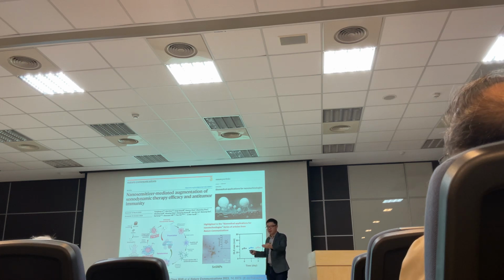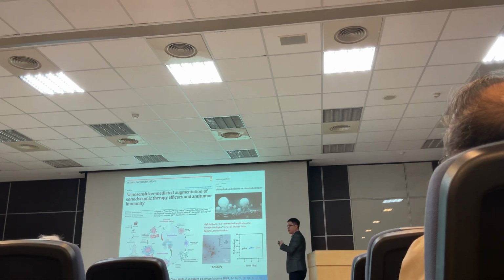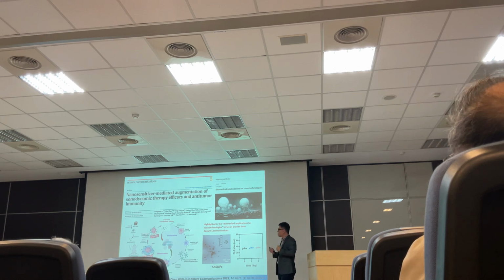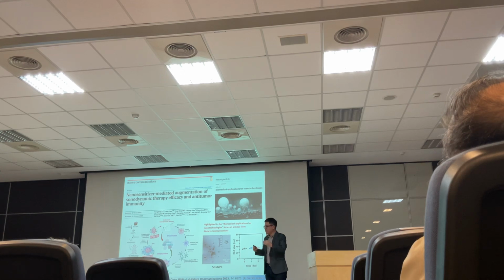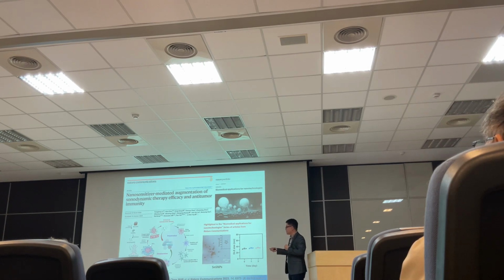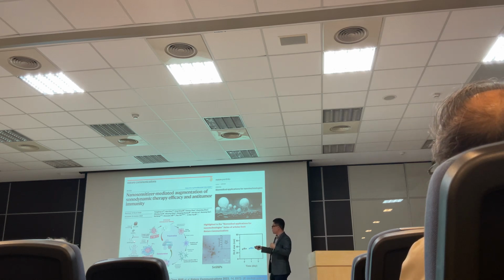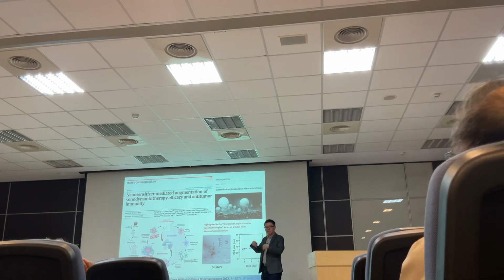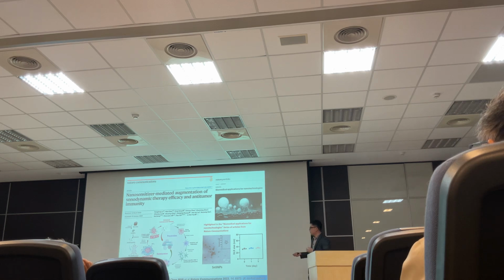As I mentioned, with a semiconductor we can use ultrasound to activate these materials, and then they generate electron-hole pairs and react with the surrounding water and oxygen molecules to generate cytotoxic ROS. Also, we discovered this particle has a very mild photothermal efficacy. This temperature is high enough to denature the surrounding stroma barrier, because in the stroma barrier there are fibroblasts and collagen. So we can use the mild photothermal effect to denature this stroma barrier and increase the infiltration of more CD8, CD4 T cells.